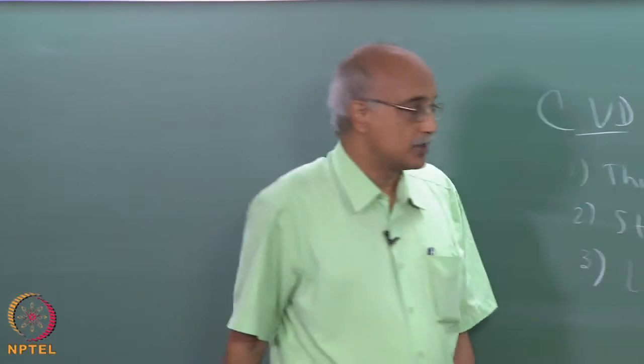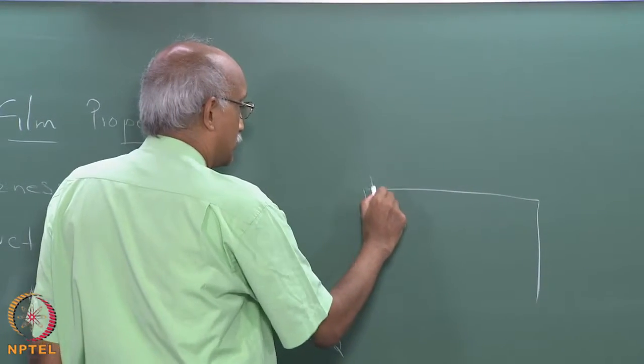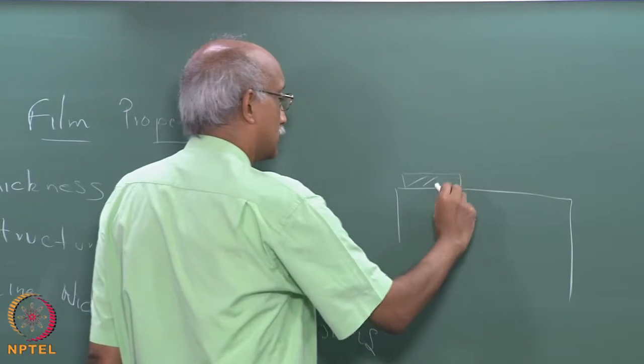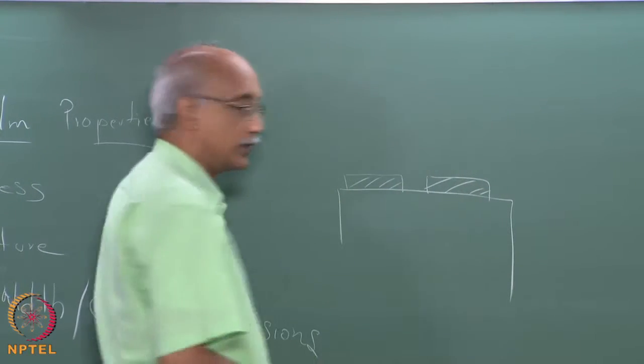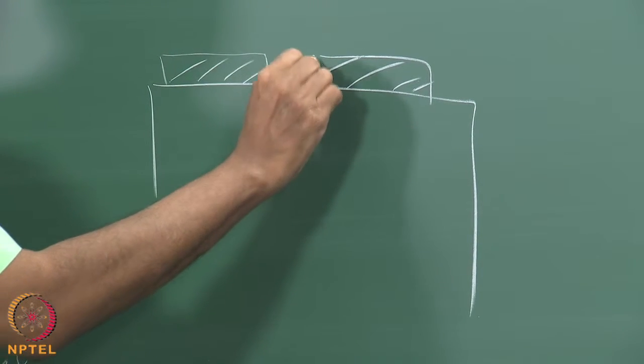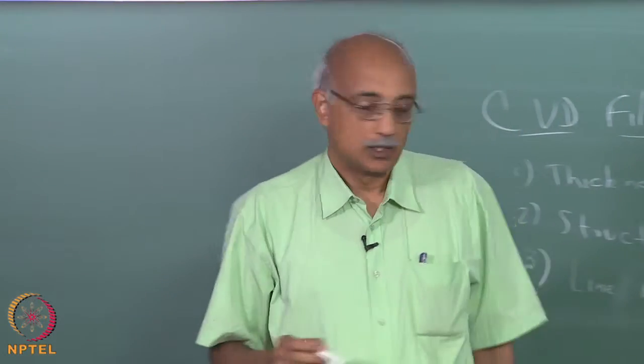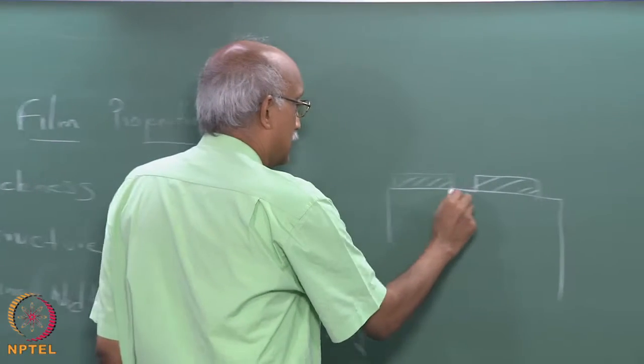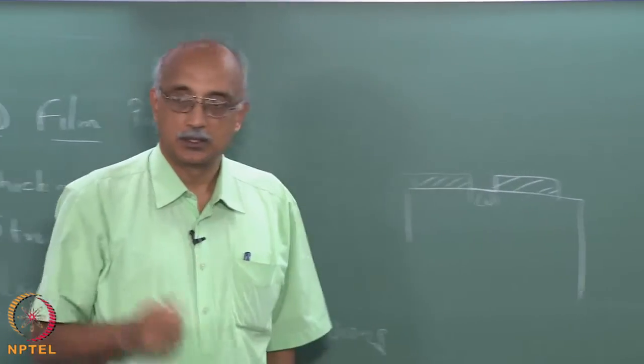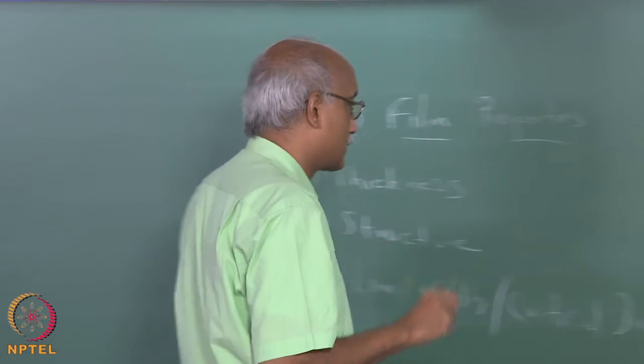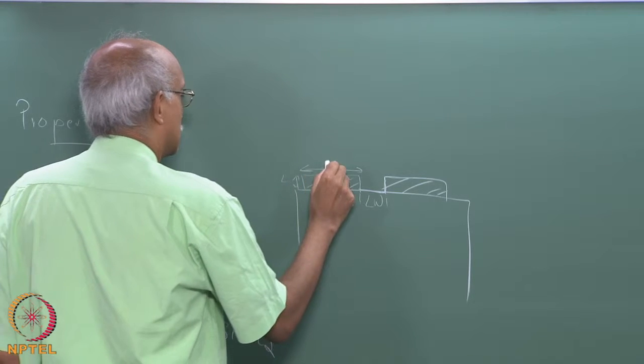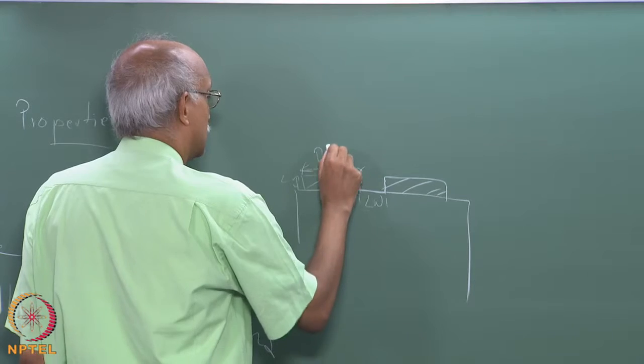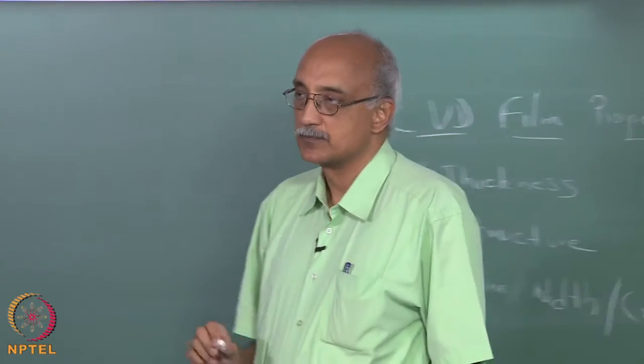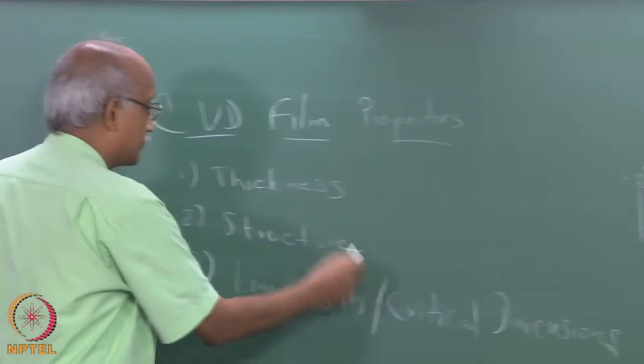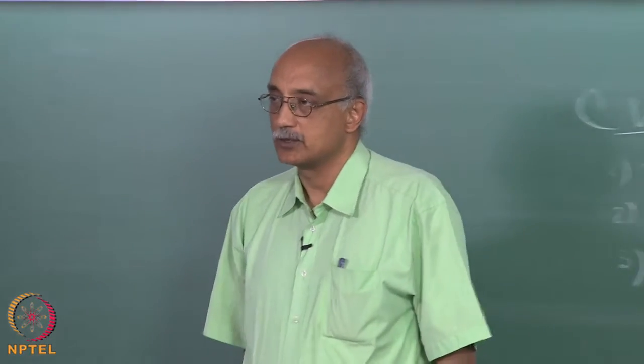So what we mean by line width critical dimensions is, if you have a substrate and you are trying to put down a film on top of it, there is usually a pattern to the film. So you may have a certain thickness up to here, and then the thickness may drop to 0 here, and then again rise to a certain thickness later, right? So in this particular case, the line width as it is defined is the distance of separation between the two CVD films. The critical dimension is typically this and this, the length, the width, and of course, since this is three-dimensional, the height or the thickness of the CVD film. So, these are the critical geometrical dimensions that you try to measure on a surface. So, thickness, even though that's listed separately, is actually one of the critical dimensions that you want to be able to measure on the substrate.